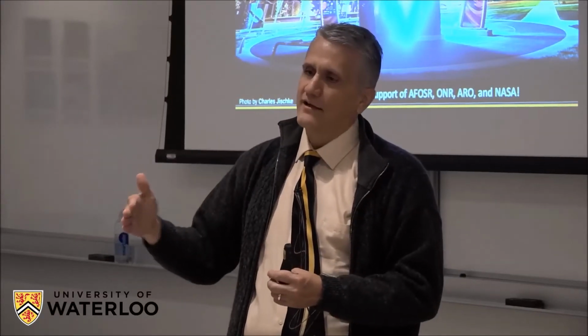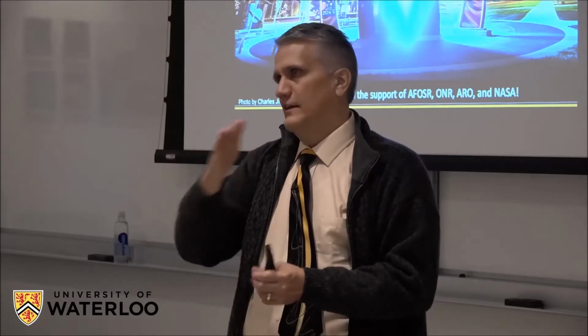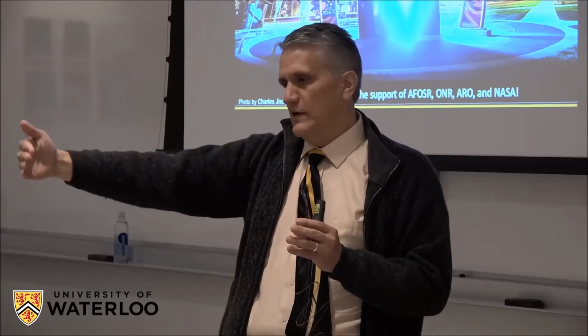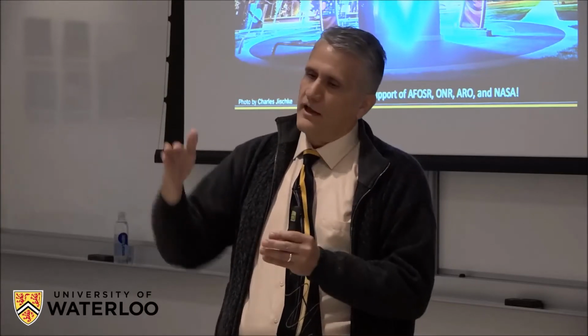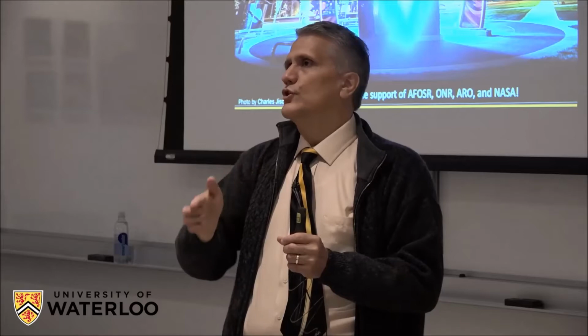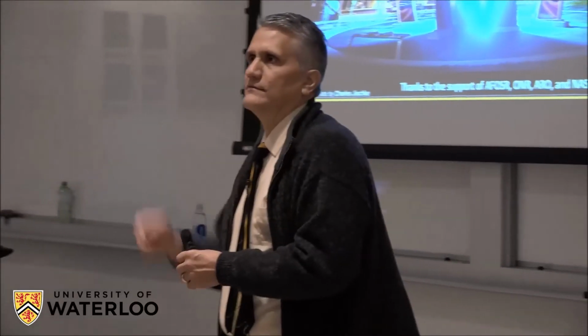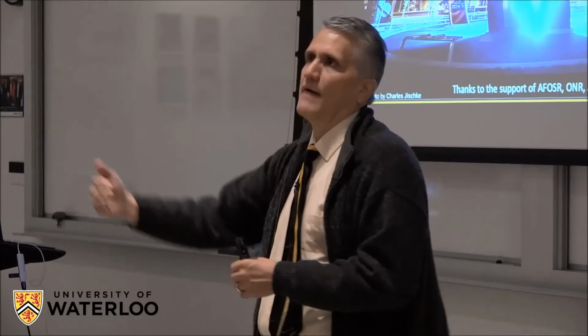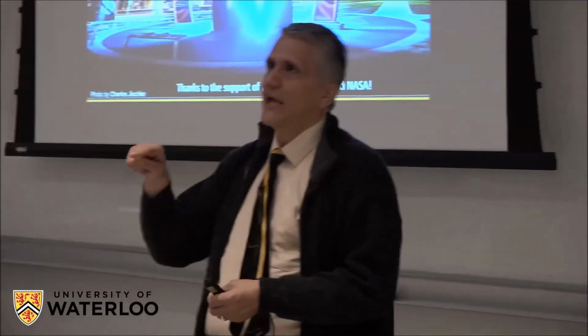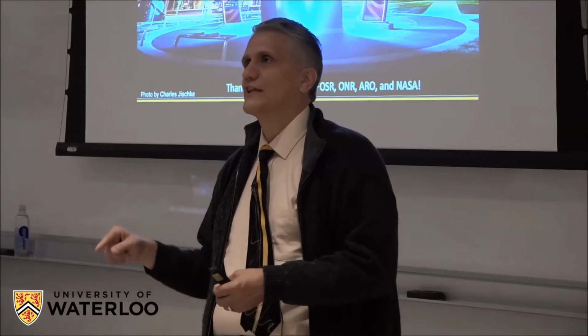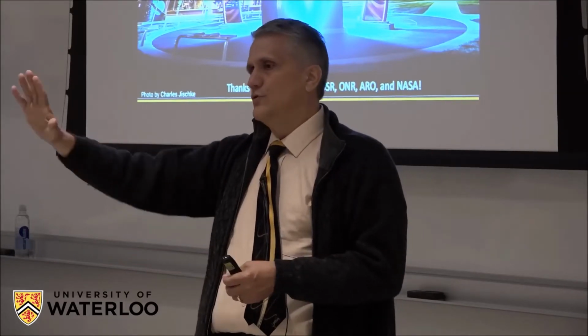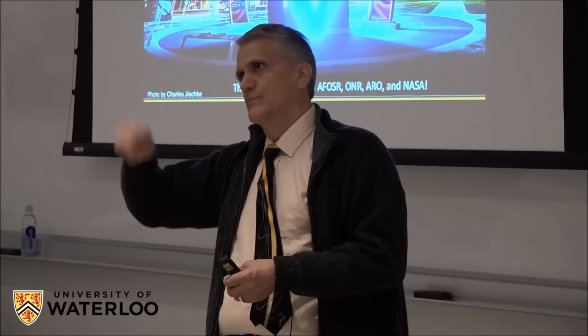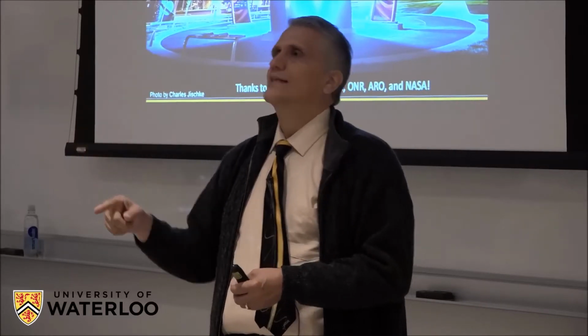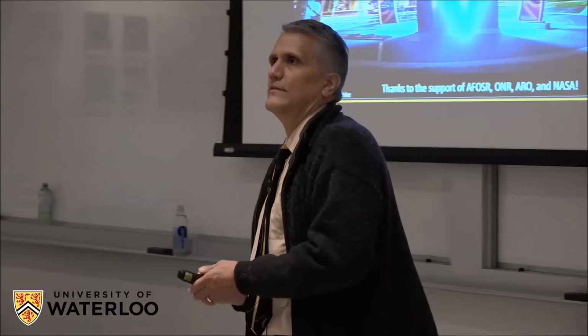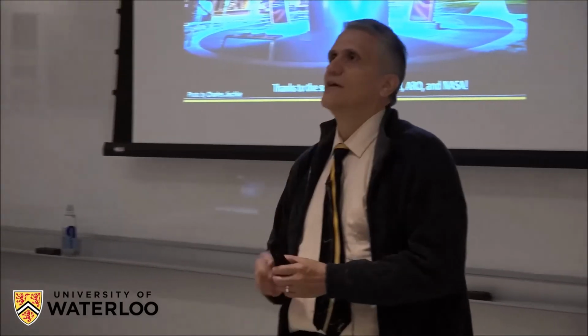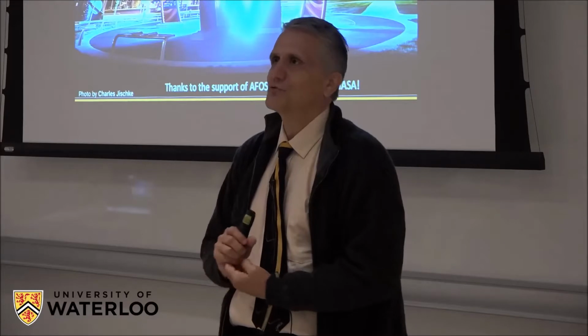We back off from that a lot. We know where our limit is on the time of milling and so forth, and then we back off from that a lot, and look at how much of that material has reacted as we change the milling time or milling parameters. We use a DSC TGA, differential scanning calorimeter and thermogravimetric analysis, to see what we are doing in terms of the onset of exothermicity, and whether we are cutting into the energy by this premature oxidation. So you have to watch that very carefully, and it's a safety issue as well.